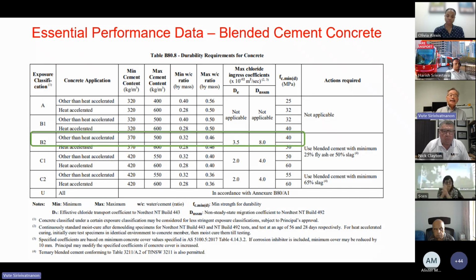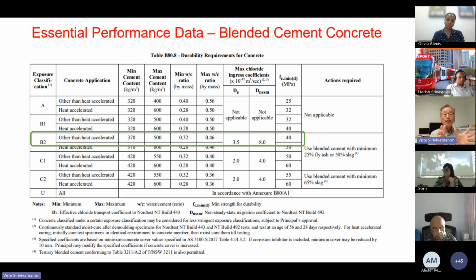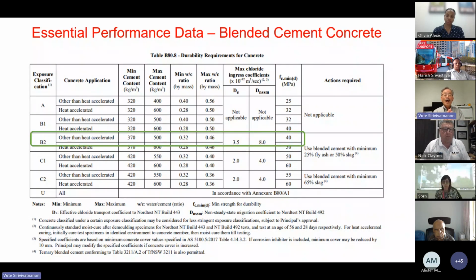Now, if we look at a typical specification for concrete, I use the example here of the Transport for New South Wales B80 specification. And in particular, I just chose a particular exposure of B2. What you can see is that the specification consists of two parts. One is the prescriptive requirement in terms of cement content and water to cement ratio, as well as the performance-based requirement in terms of strength grade and, in this case, maximum chloride diffusion coefficients, depending on the specific test method that is required.